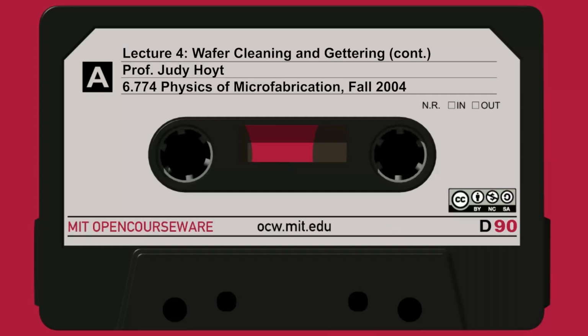So I can write this equation for those two cases, and it has to hold. Basically, it turns out that the ratio of the Au minus concentration in N-type material to its concentration in intrinsic material just has to go like N over Ni.